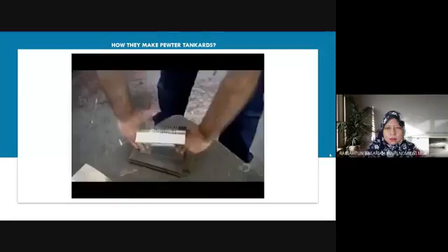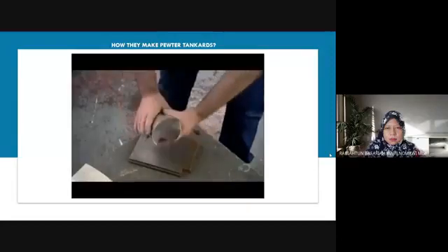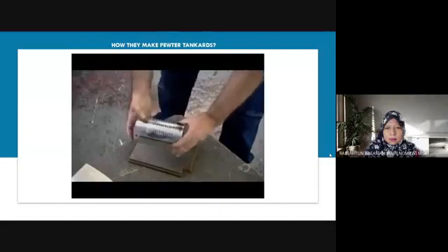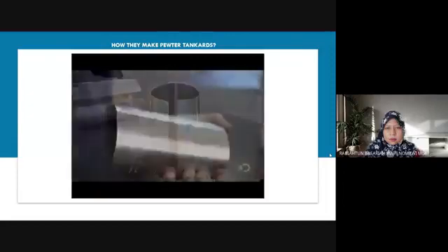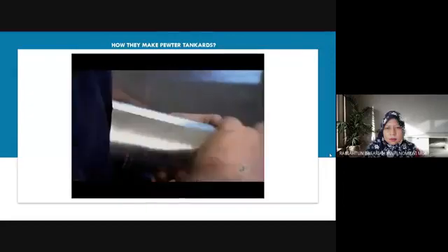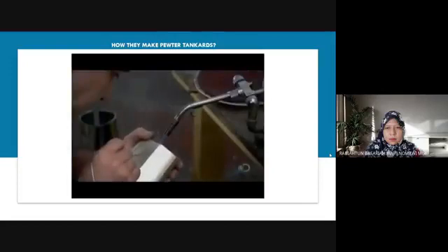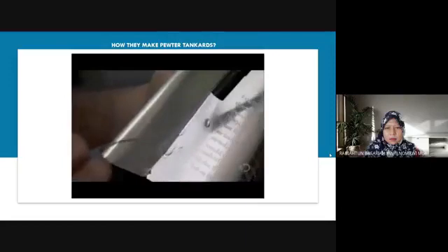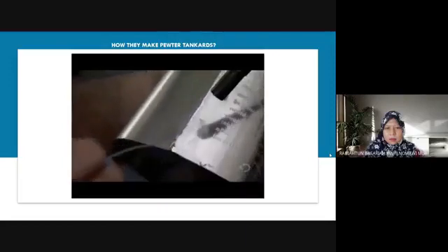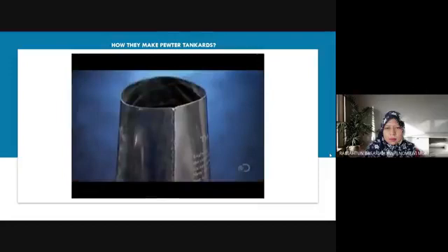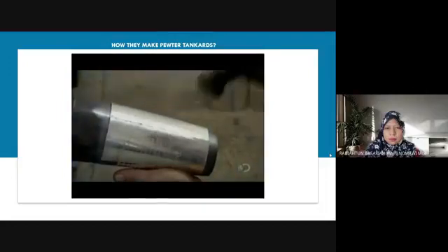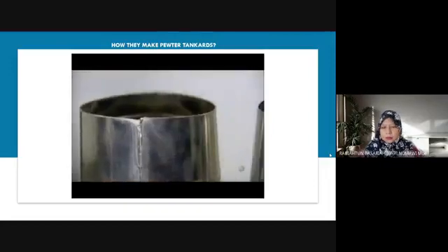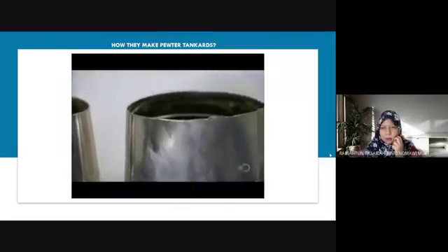Next, a metalsmith takes over. He manually bends the pewter into the cylindrical shape of the tankard's body. He brushes on flux, a chemical which helps molten metal flow more easily. Then, with a soldering tool, he fuses the edges of the body with pure tin solder. Traditionally, both the pewter and solder contained lead, but today, both are lead-free. Next, the metalsmith slides the cylinder onto a steel form and hammers the solder seam flat, rendering it virtually invisible.